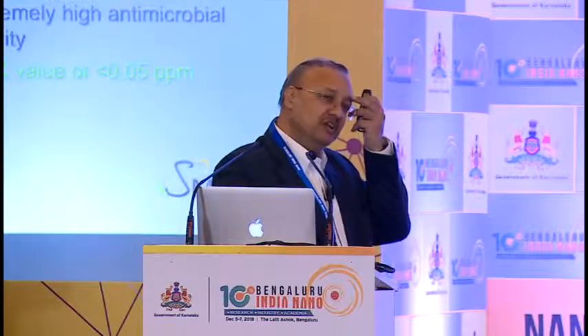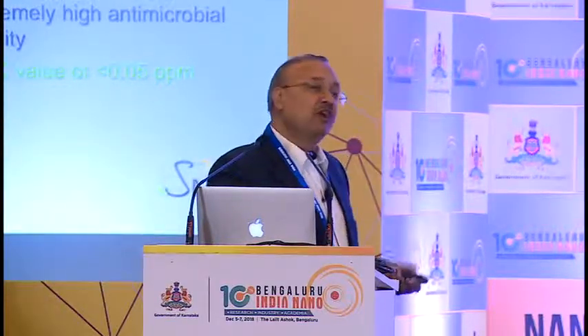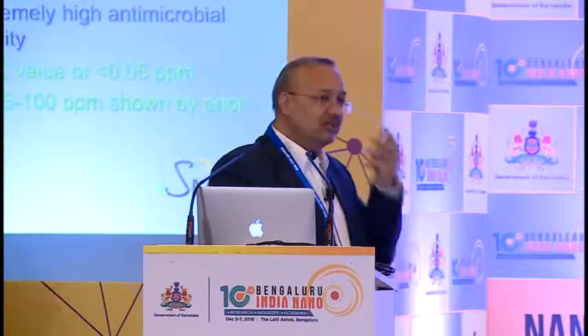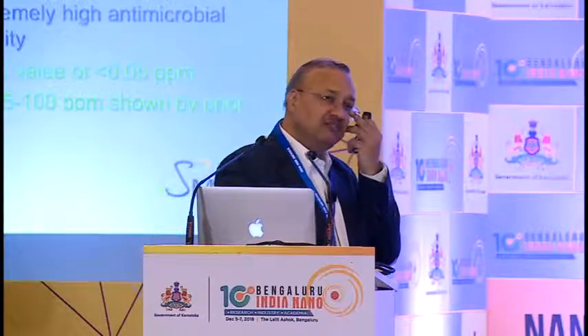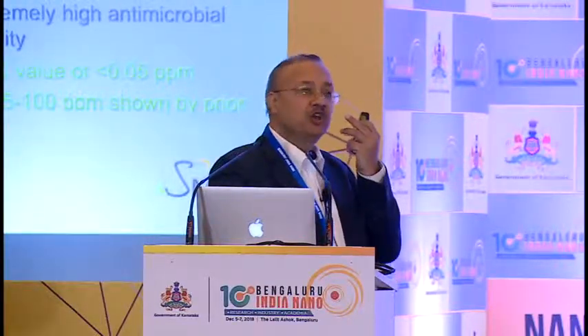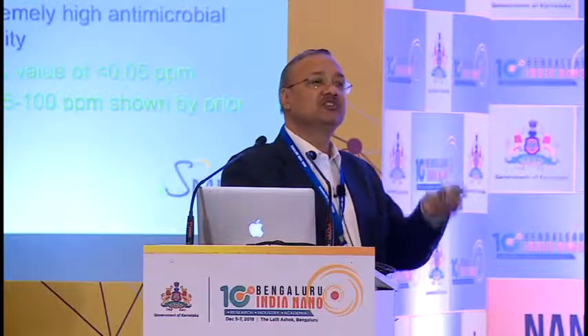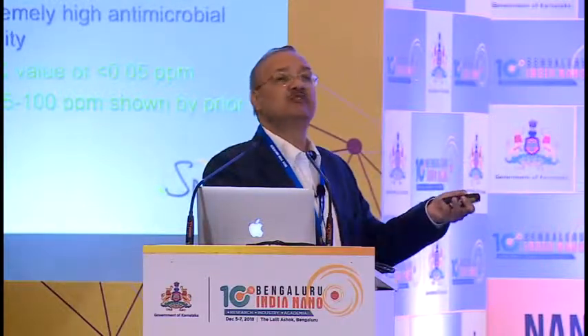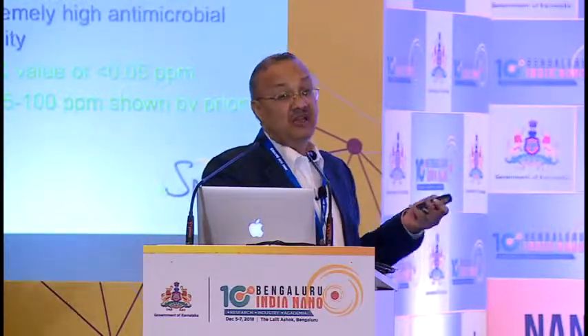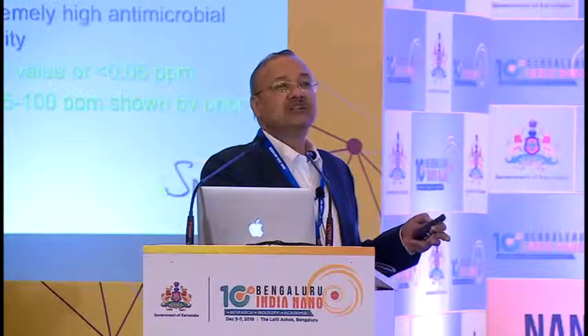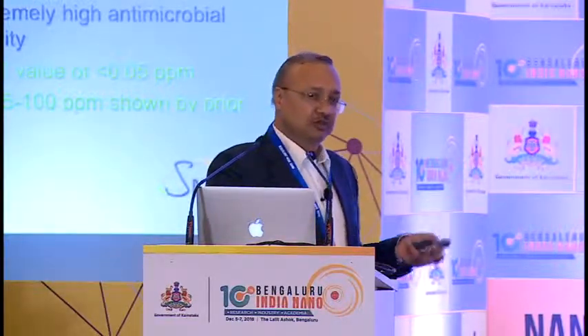It has very high color stability and a very high antimicrobial effect. Actually, the MBC value is the lowest reported in the literature. It's less than 0.05. And if you look at all the other literature, there's nothing reported less than 5 ppm. So we are talking about 2 orders of magnitude lower concentrations, as effective as any other silver product in the market, anywhere in the world. And that made this technology extremely successful, and all the multinationals could not stand in front of it.